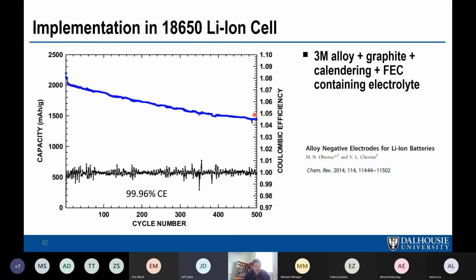So here's 500 cycles from an alloy in an 18650 cell. It's only a 2 amp hour cell. This axis shouldn't be milliamp hours per gram, it should be milliamp hours for this cell. The interpretation of this capacity fade is that it's virtually all from lithium inventory loss on the negative electrode. That's right, continually growing SEI. And what it means is the mechanical properties of the negative electrode are good, but that also means SEI growth is out of control.